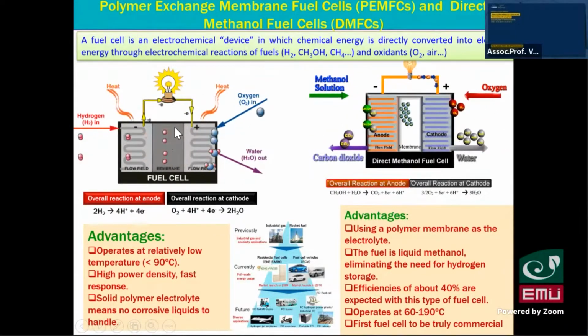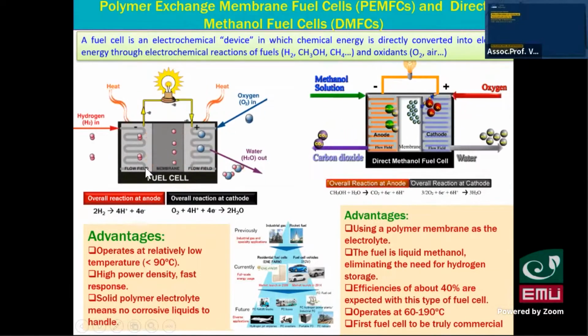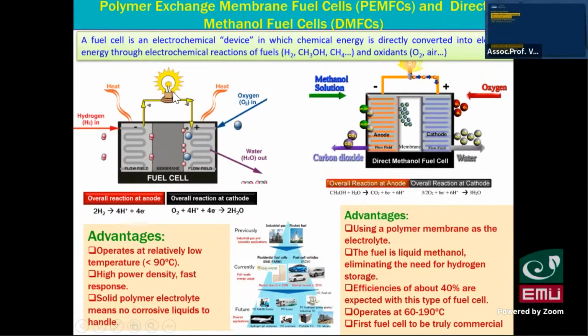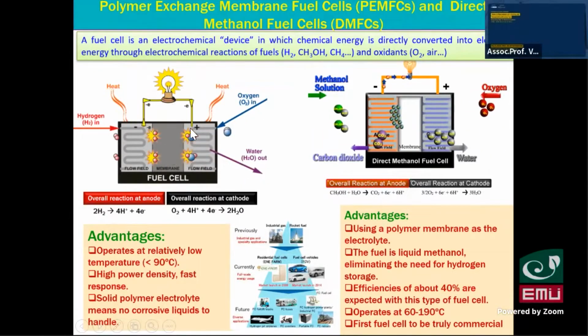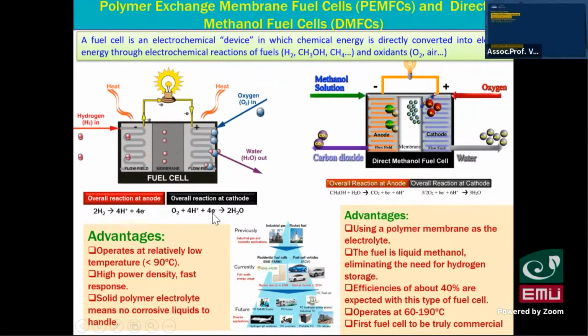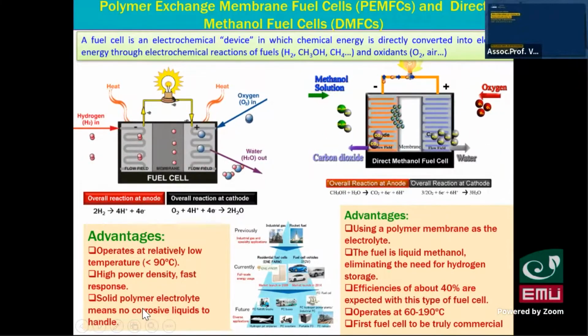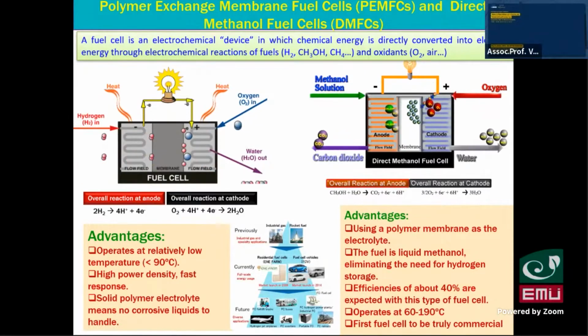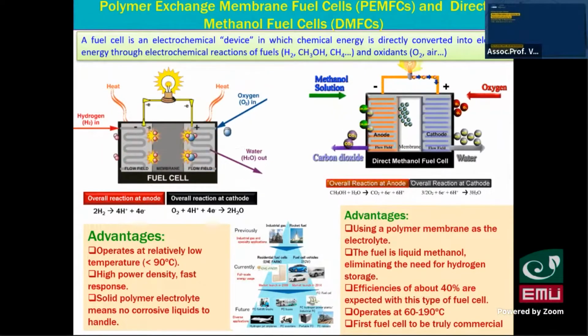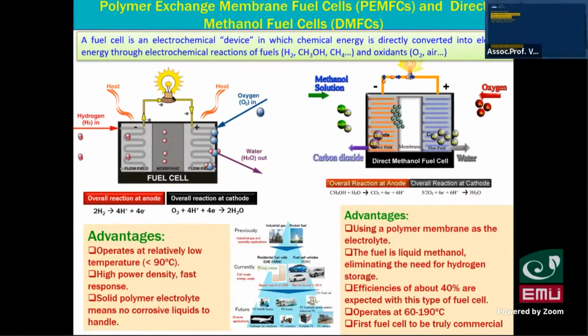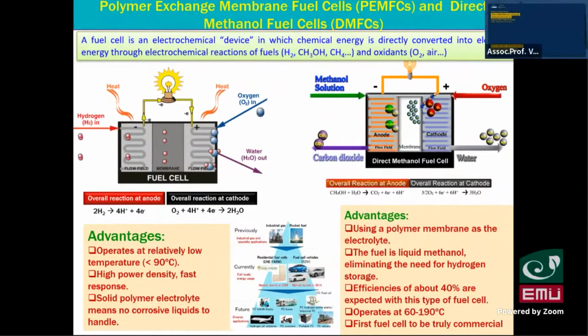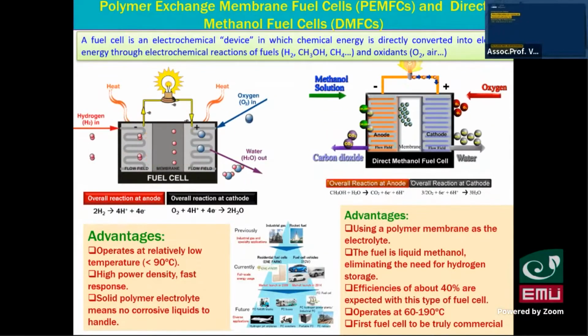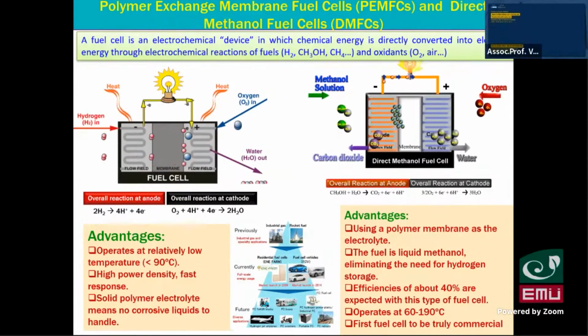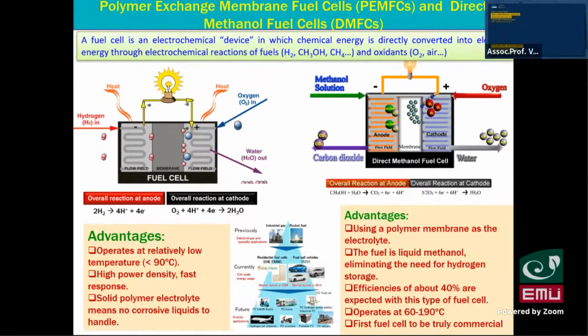This membrane doesn't allow electrons to go through, just the H plus ions. That means electrons need to go outside from the anode to cathode, so we can get electricity and also water out. So it's very clean energy. This system has very high efficiency, high power density, and fast response. The operating temperature is also low, below 90 degrees C. And the solid polymer electrolyte means no corrosive liquids to handle.